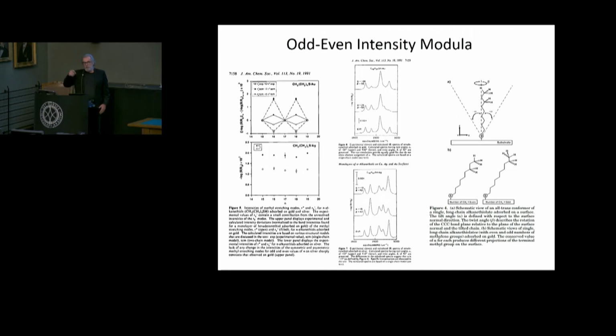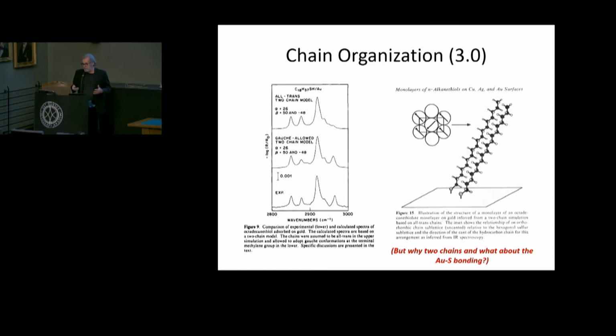And when we did odd-even, you see odd-even progressions in the intensity ratios that correspond to that fixed angle, right? Because in one case, the methyl group will point this way, and in another case, it'll point more along the surface normal direction for a fixed angle of tilt. And in gold, that's true, and on silver, that's not true. And that's actually an interesting part of how these metals differ, but the whole point is that you're making this sound like a really complicated story that's emerging in a relatively direct way from this characteristic spectroscopy.